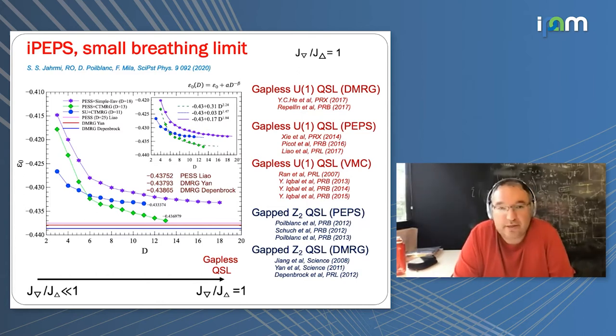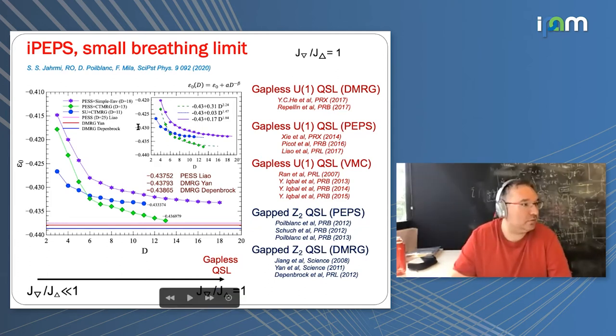First, we consider the case of no anisotropy at all, just to benchmark our method. That means that this ratio is equal to one. Now, this is the true Kagome Heisenberg antiferromagnet. And of course, this is the ground state energy as a function of the bond dimension of the tensor network. Here you can see the results with different techniques: projected entangled simplex states plus some simple environment. This is some mean field environment, no contraction at all.